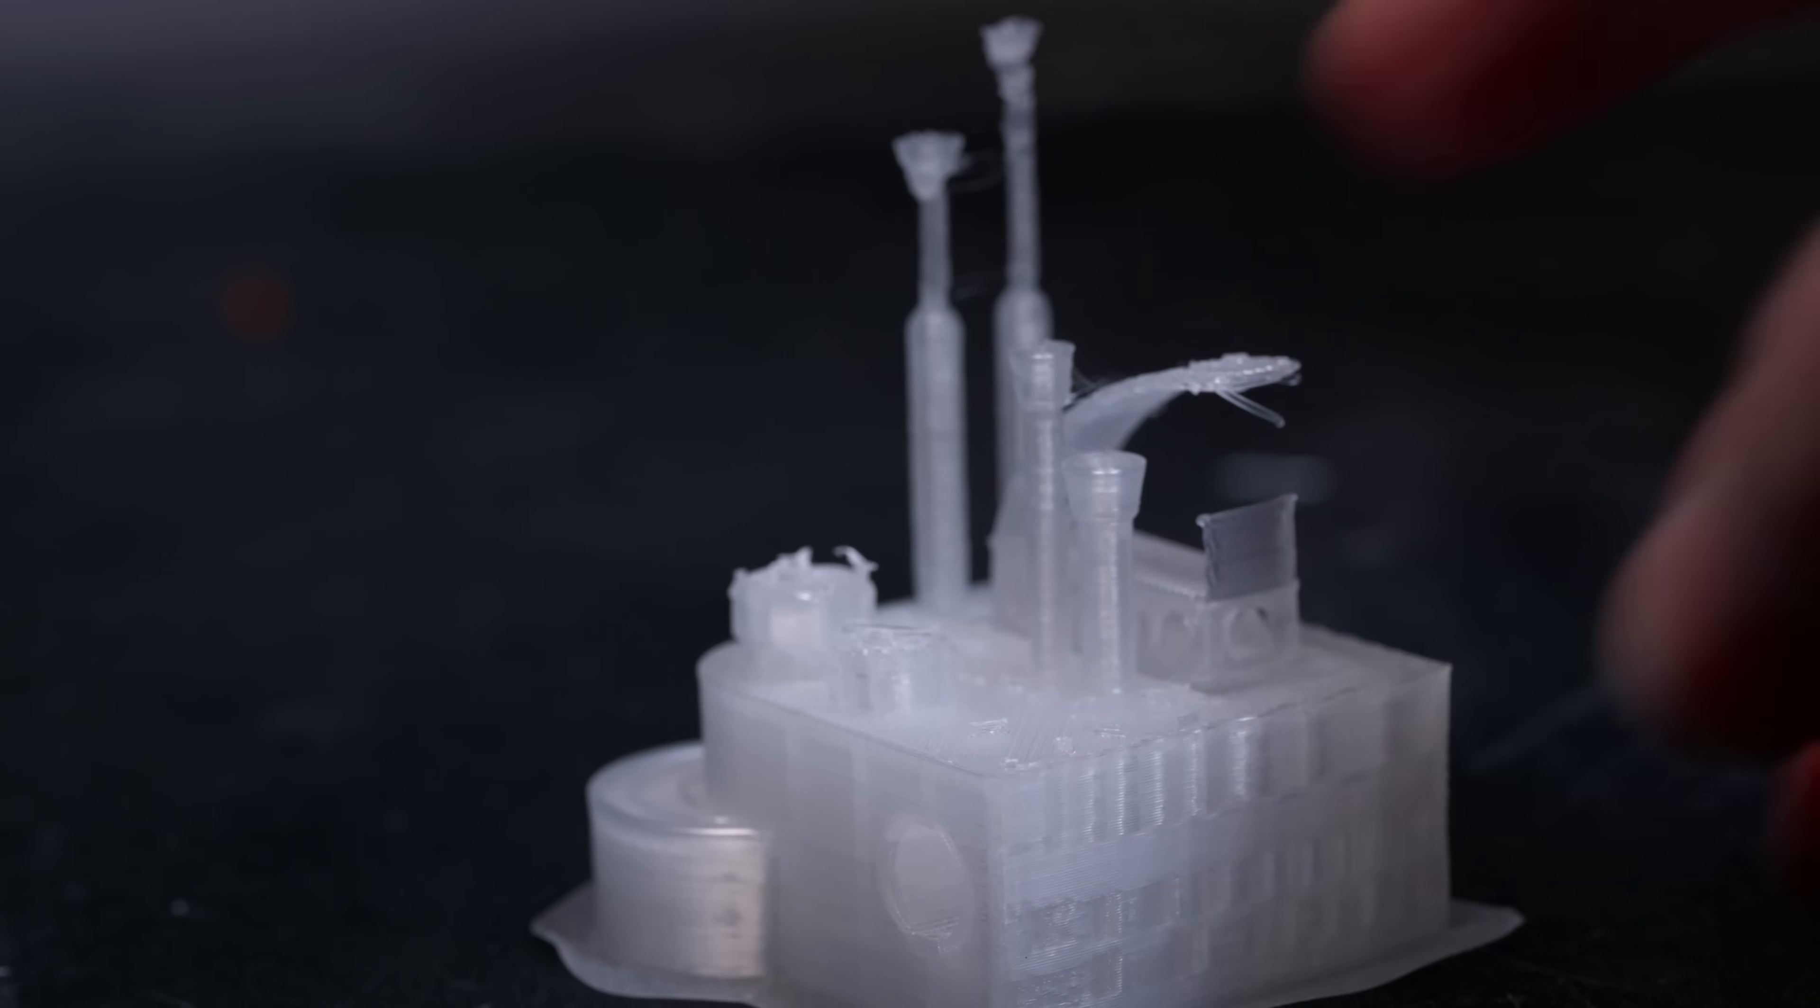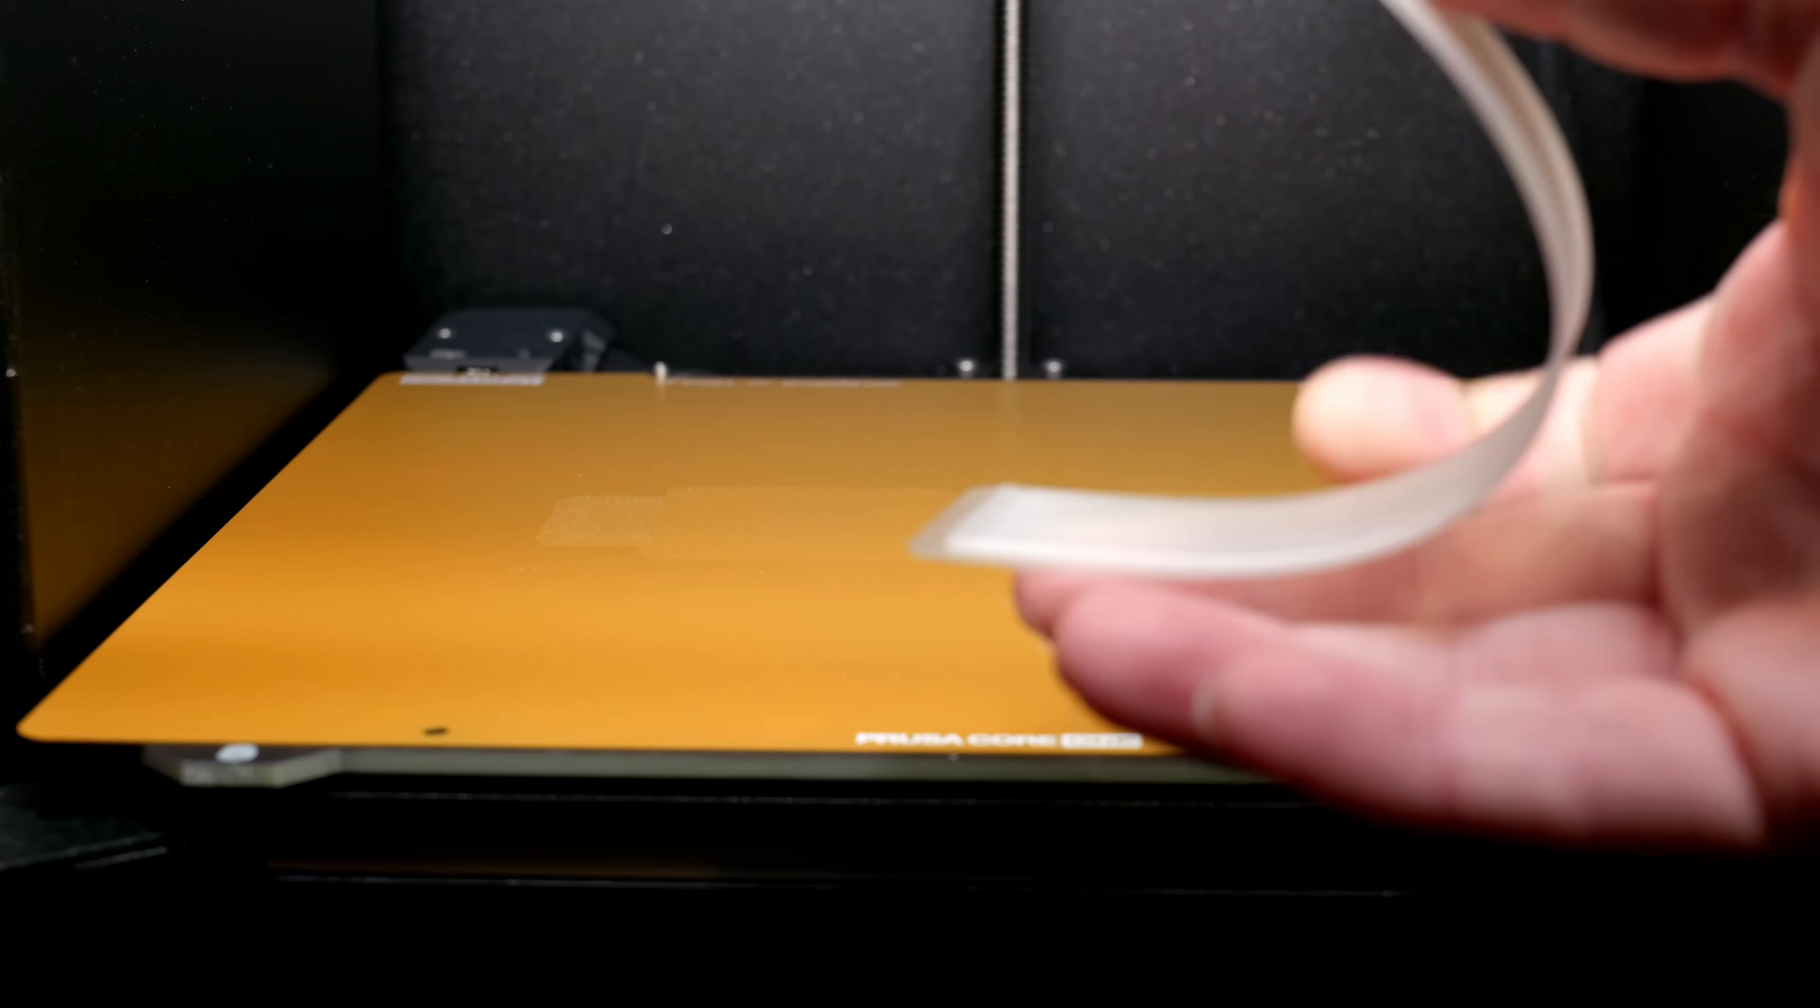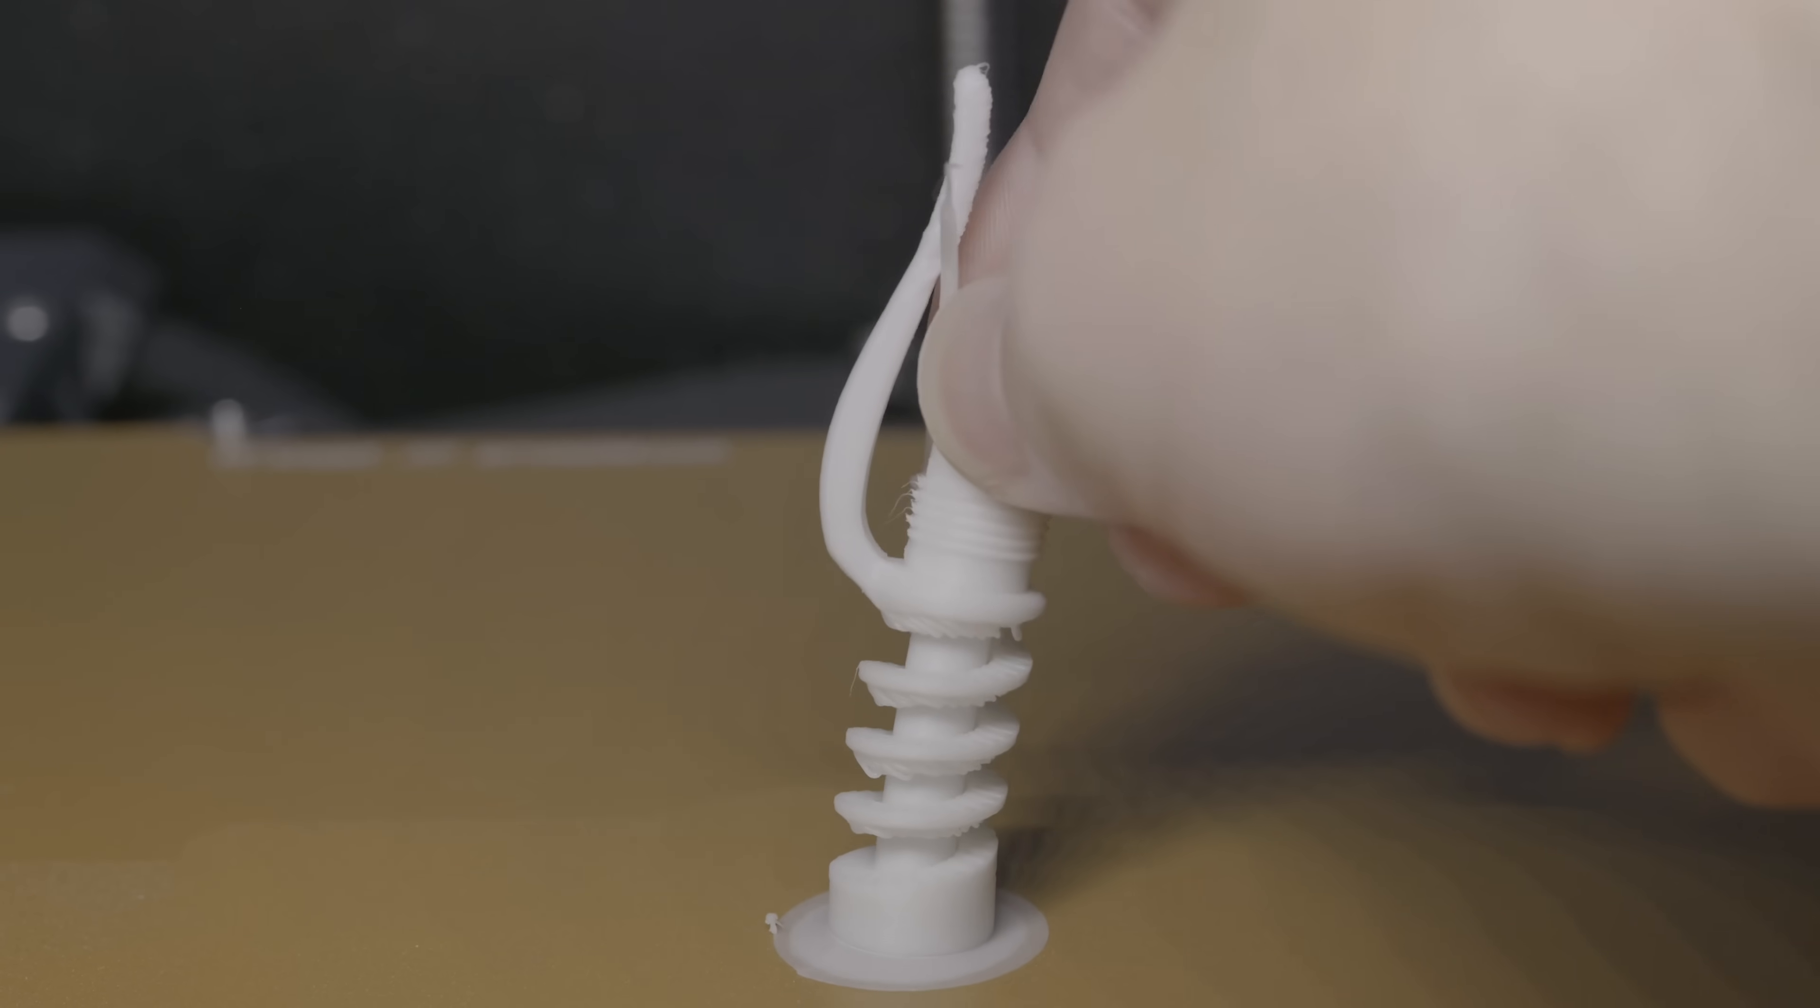And finally, it's really cool to be able to bend these parts without them snapping. Polypropylene's main advantage is that it's virtually indestructible by deformation as long as you aren't doing so along layer lines. You can snap the chimney off a benchy fairly easily, but if you have a long flat piece that you print out like this, you cannot destroy it by bending it at all. And this is the other reason we've got to this episode. This is preparation for the upcoming episode on compliant mechanisms. So polypropylene is really perfect for that kind of thing because it just won't break if you're using it in a compliant mechanism kind of design. So yeah, all that deduced from one test print. Whoever made this test print must have been quite smart.